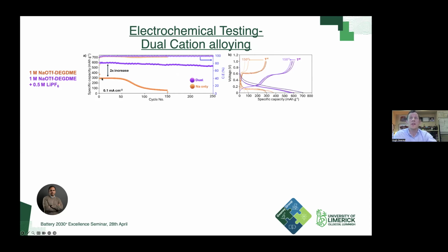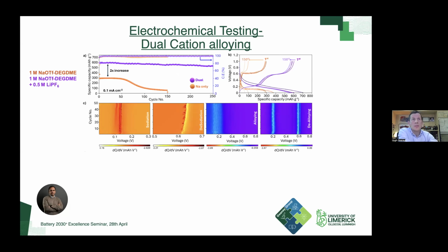And what you can see is as soon as we incorporate the secondary charge carrier into the system, we get a doubling of the specific capacity that we can achieve. We also get a dramatic extension of the reversibility. So this matches what we had seen before for germanium in sodium cycling, but once you bring in these dual ions, we have dramatically improved the performance.